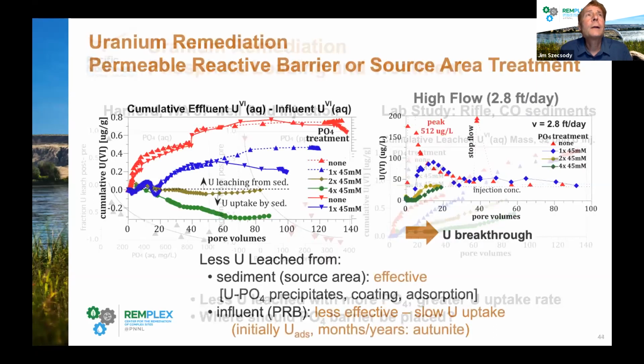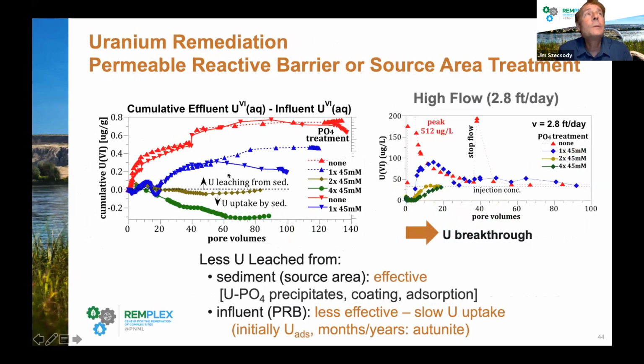But I analyzed the data a little differently. This is the same data, but instead of just plotting cumulative effluent, I plotted effluent minus the influent uranium. So we could separate out how much uranium is leaching from the sediment, and we filtered out the uranium that was coming in as influent. So again, untreated, low, medium, and high phosphate treatment, and more phosphate, less uranium leaching.